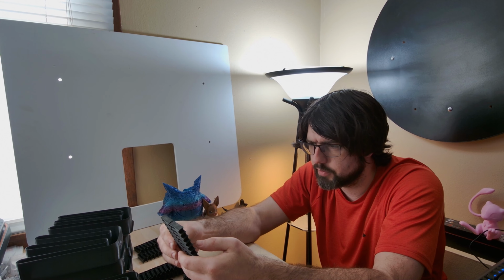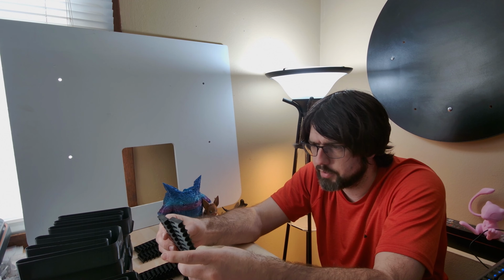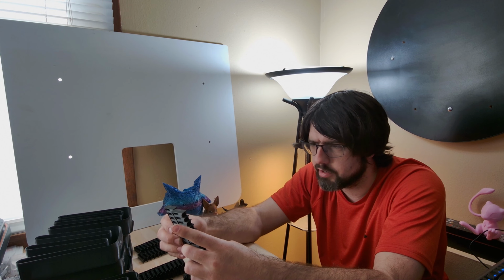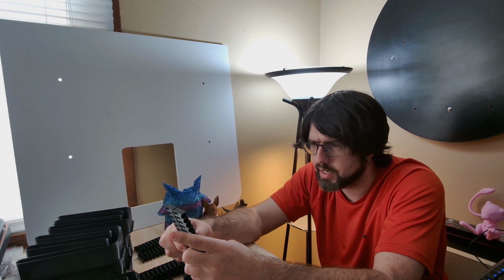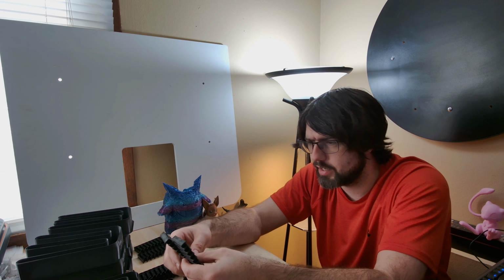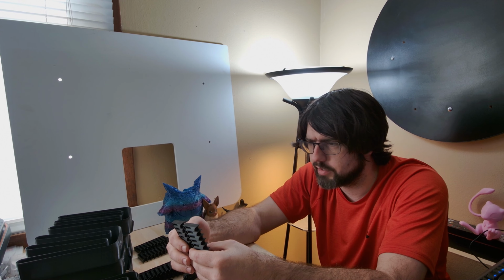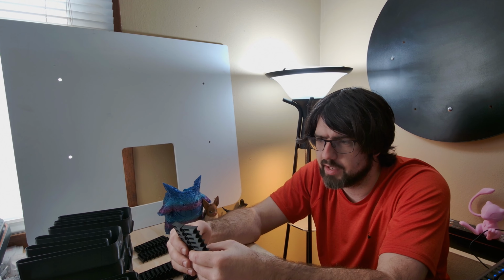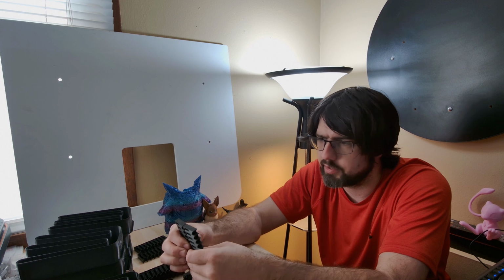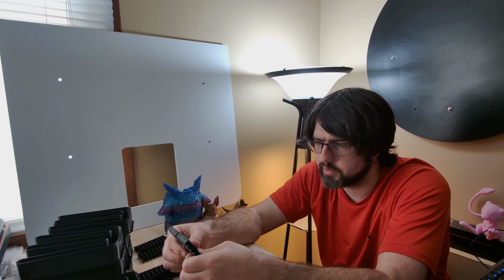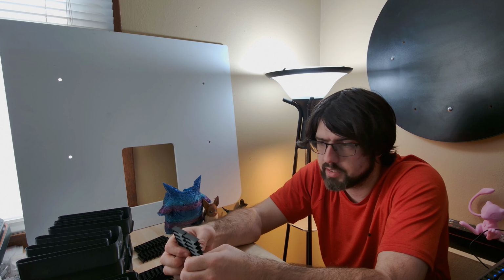And PLA, Red and Hyper, both performed similar. Hyper, again, stringing just starting at 220, and same with the Red. They both performed extraordinarily well, clear down to 180 degrees. The Red PLA had a little bit of under extrusion right around that 195, and I don't really have any signs of it except for maybe a little bit at 180 with the diamond, with the Hyper PLA. So the test pretty much coincides with what we expect.